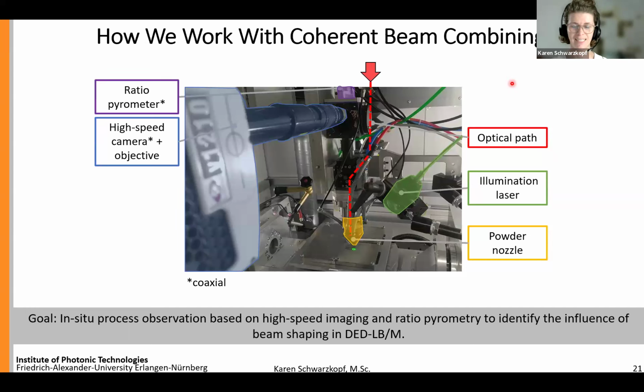Okay, this is how it's generally looking, but at the moment we are more interested in understanding how these different beam shapes influence our material processing approach. Therefore, we employed a high-speed camera system that allows us to coaxially observe our process zone, which is highlighted here by the green dot. We also employed a ratio pyrometer in order to get thermal information from the process. Additionally, we employed an illumination laser to visualize different aspects of our melt pool.